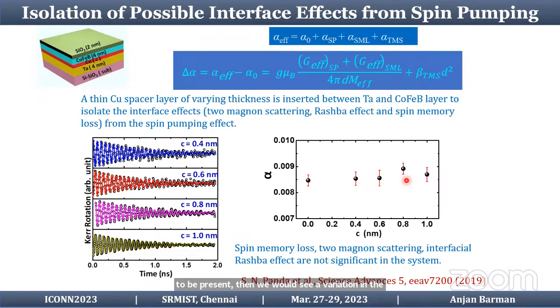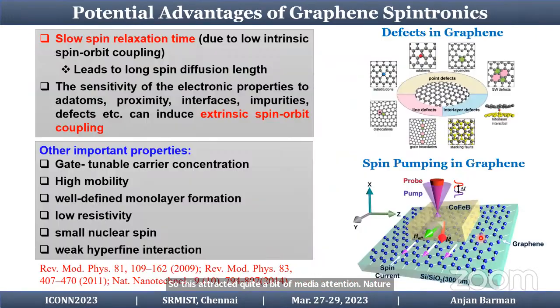But here we see that the damping doesn't vary with the copper layer thickness, which sort of proves that spin memory loss and two magnon scattering have negligible or insignificant contribution. So this attracted quite a bit of media attention, Nature India and Deccan Herald.